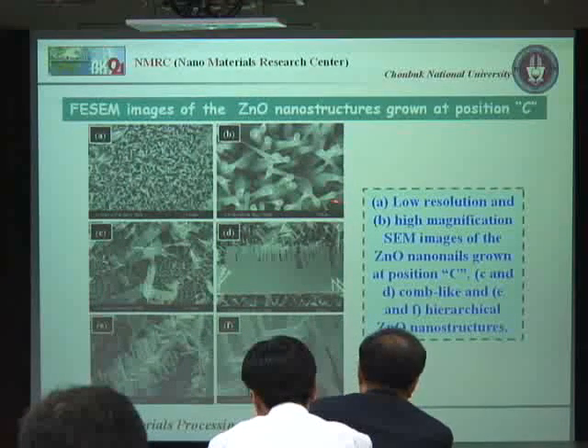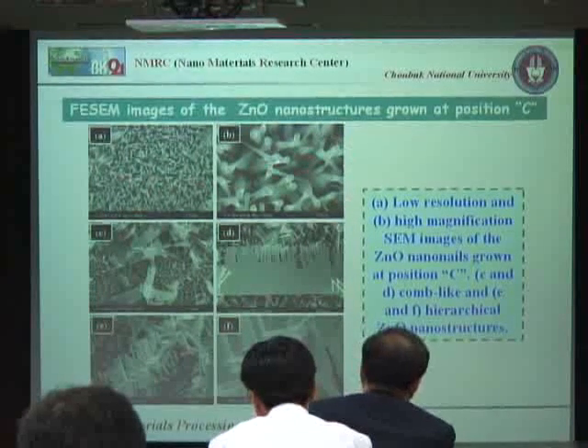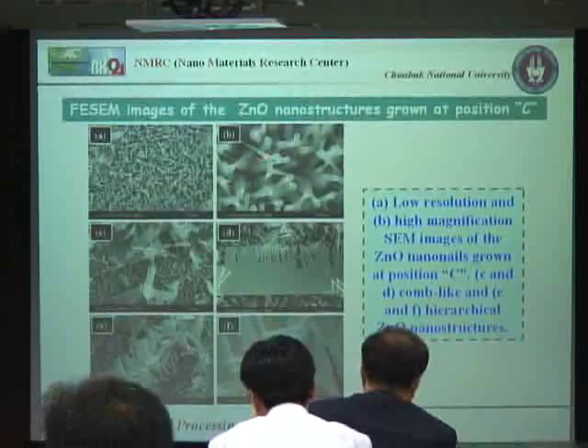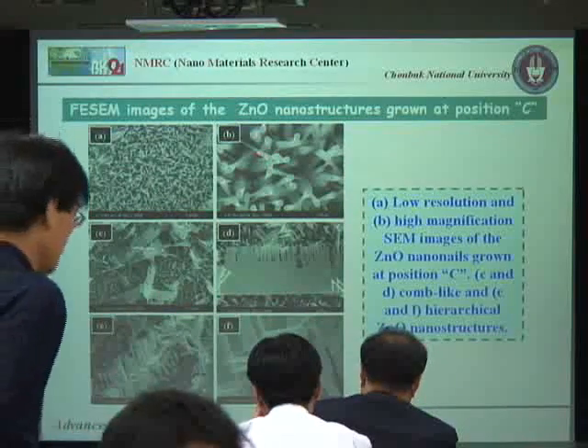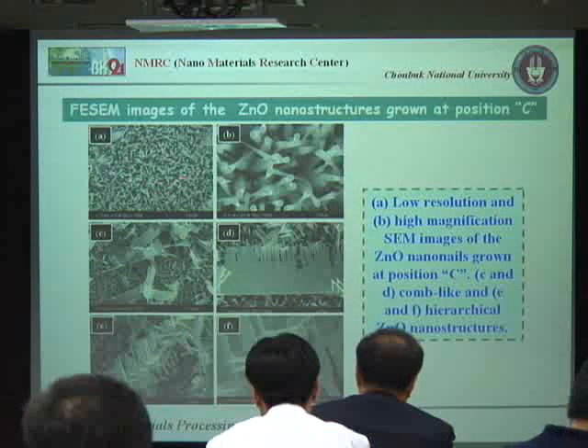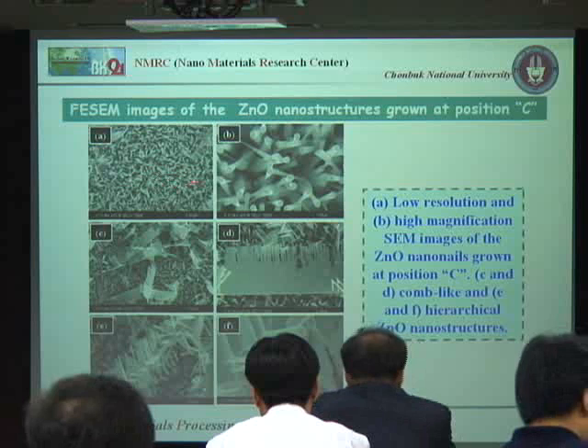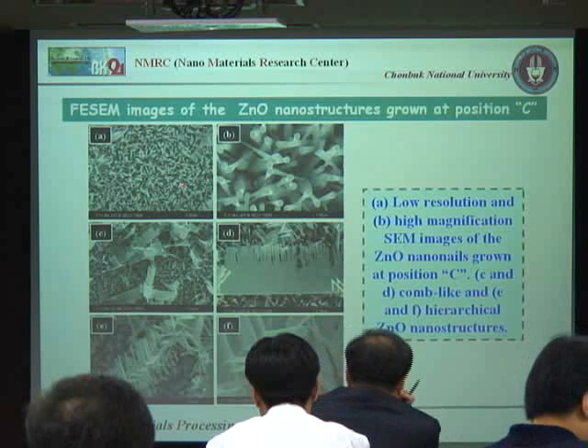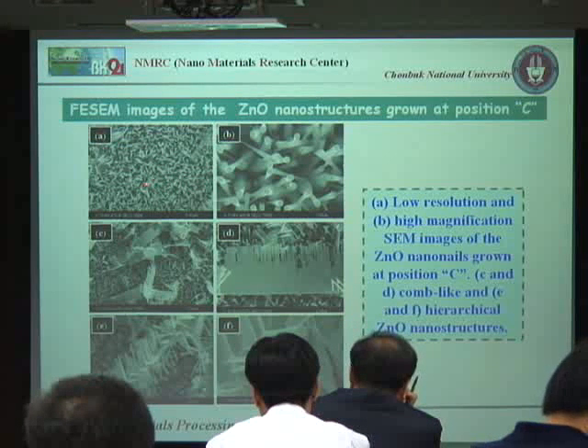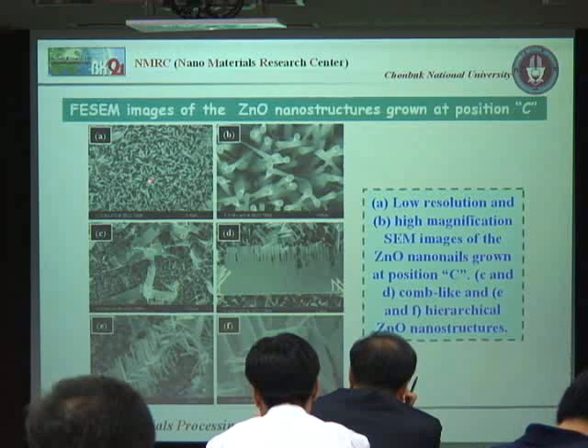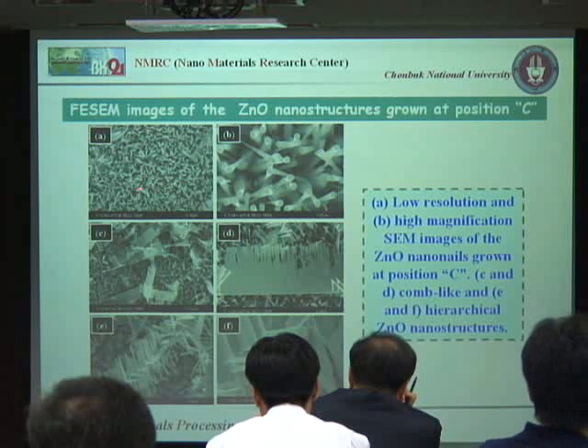At position C, we got also this nail-like structure, but we can say inverted cone-like structures. These structures also originated in very high density on the whole substrate surface, but the alignment of these nanonails is a little bit poor. They are not fully aligned, but they are partially aligned to the substrate.